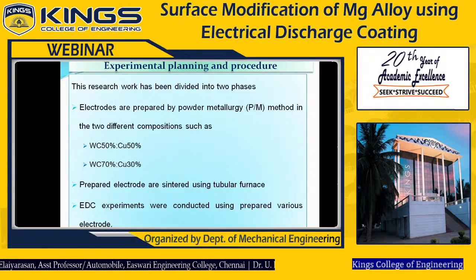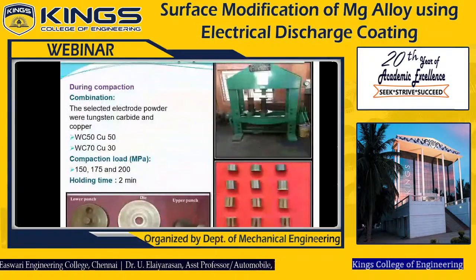Another proportion: 70 grams tungsten carbide and 30 grams copper. Okay, the electrode is prepared using the powder metallurgy technique. After the electrode is prepared, the electrodes are sintered using a tubular furnace with an argon inert atmosphere. After sintering, the electrodes are subjected to the EDM process under various conditions. So electrode preparation, you can see in this slide.